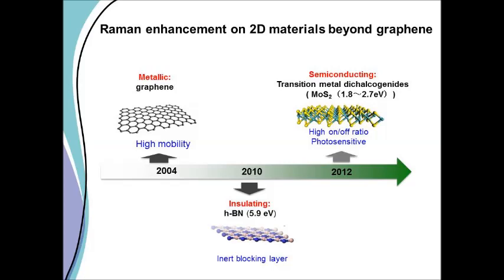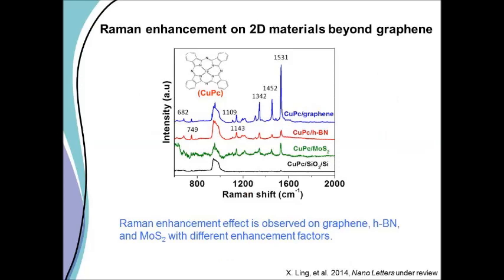And at this conference, we had people talking about graphene and then beyond graphene. So here we have some beyond graphene. So we had MoS2, and we've done a whole bunch of different dichalcogenides. Graphene works the best, but the other ones also show this enhancement factor. But not everything shows an enhancement factor. Only those things that have hexagons, so we have hexagons here, that's graphene. And MoS2 has sort of hexagons. When you look at it from the c-axis down, they don't quite match the unit cell distance, but they are hexagonal. So graphene works better because we get the matching. But the others do have a similar symmetry, so we get some component.